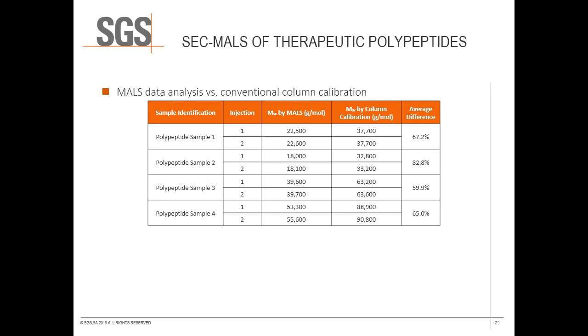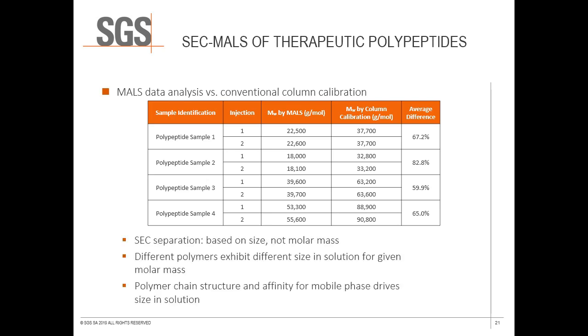As you can see, a significant difference exists between results calculated by MALS and by column calibration. Any error in molar mass values calculated by MALS associated with error in the dn/dc value is dwarfed in comparison with the estimation of molar mass using standards. The molar mass values calculated from column calibration, if presented alone, would give a false idea of the character of the sample.